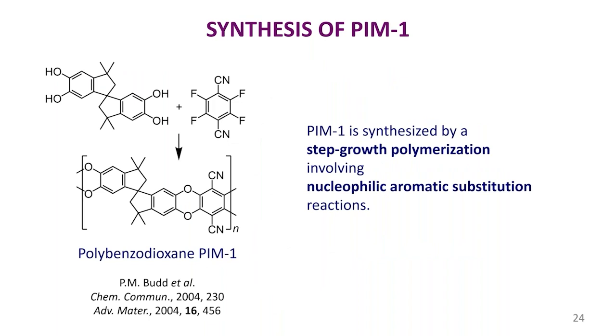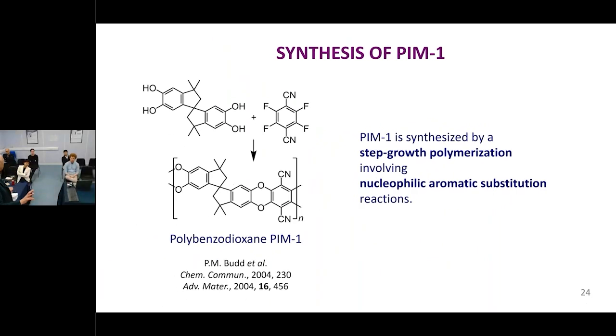And in the case of PIM-1, we started with two monomers, and this is one of the beauties, that they're not particularly cheap, but they're commercially available. A lot of the other PIMs involve chemists spending an awful lot of time synthesizing bespoke monomers. But we have two monomers, one of which contains the spirocenter, and in this case, we're doing a bit of chemistry which is known as nucleophilic aromatic substitution. So we have a couple of hydroxyls on one molecule, a couple of fluorines or chlorines, nowadays we tend to work with chlorine as much as possible, on the other. And you'll see there's also a CN, a nitrile group there, which actually activates that monomer towards this type of chemistry. So it works very efficiently at temperatures that are lower than would normally be used for this type of chemistry.